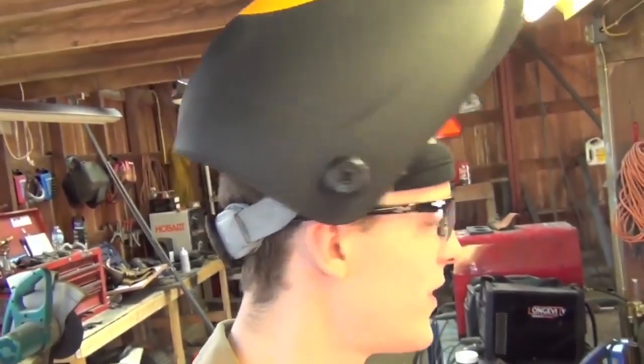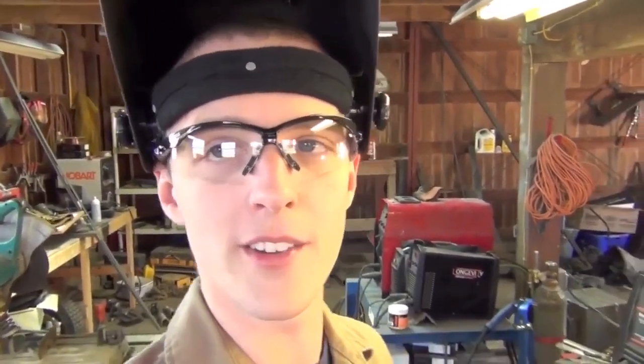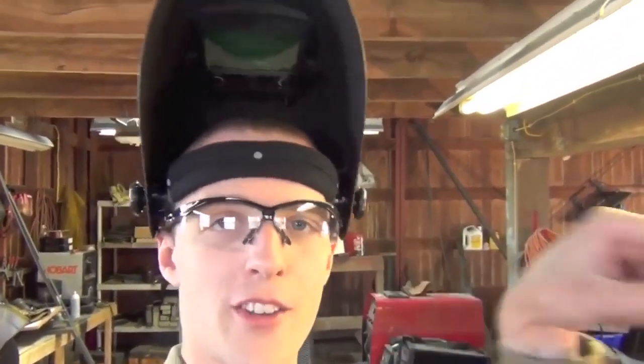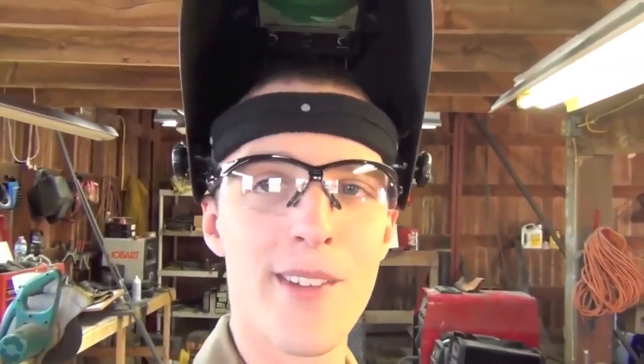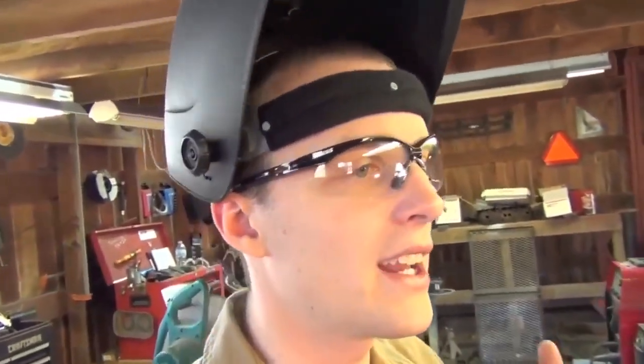it's really thin wire, whatever you're MIG welding with. I mean, we're pushing probably 170, 160 amps or something right now through something that's 30 thousandths of an inch wide. It's going to get hot really fast, and if you're running way too much stick out, you're just going to be shooting little stubs of wire, the current's going to be melting them, and it's going to be a big mess. This is something you're going to get a feel for as you go along, and if you run way too much stick out, then it's just going to be, well, like this.